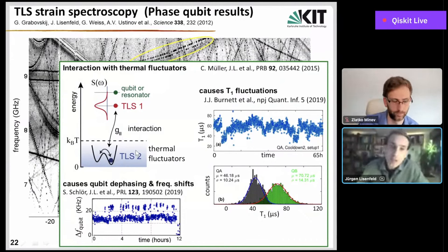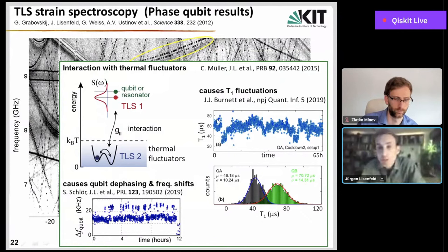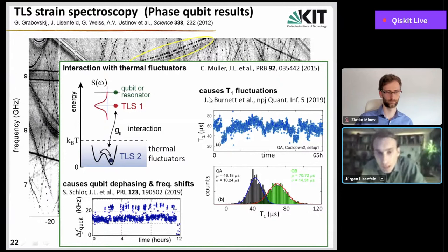And not only may the resonance frequency of this qubit fluctuate, of course. When the TLS comes closer to the qubit, the T1 decay of the qubit would be enhanced. And that's also what people have studied more intensively in recent years. So for example, this is data from Jonathan Burnett showing the time dependence of the T1 time of a qubit. And you see that, again, you have these sudden jumps or just slow drifts in the T1 time. And if you make a histogram out of these data, you again find a typical spread of, let's say, plus minus 50% from the mean value in both directions just by waiting.